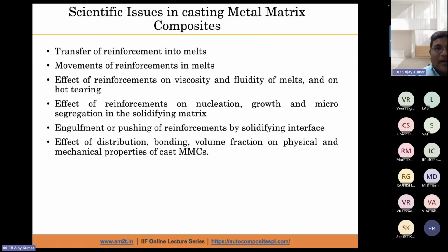Now, what are the challenges, the scientific issues, when we make the cast MMC for different applications? First challenge is transfer of reinforcement into the melts, then movement of reinforcement in the melts, effect of reinforcement on viscosity and fluidity of melts, and hot tearing effect. Effect of reinforcement on nucleation, growth, and microsegregation in the solidifying matrix. And then when we mix the reinforcement particles, we also see engulfment or the pushing of the reinforcement by the solidifying interface, and the distribution, bonding, and volume fraction on the physical and mechanical properties of cast MMCs. So these are the scientific issues, some of which people have already addressed. And when we are talking about the recent trends, some of the issues are already addressed, but some issues still exist, which need to be addressed through future research.